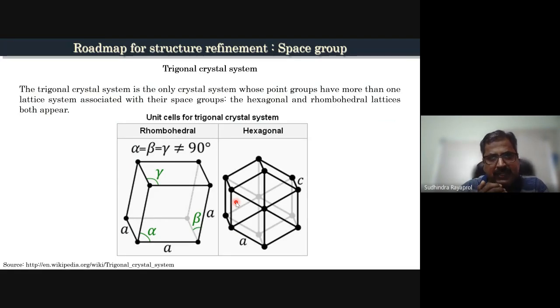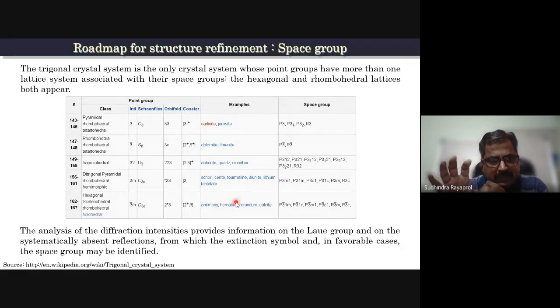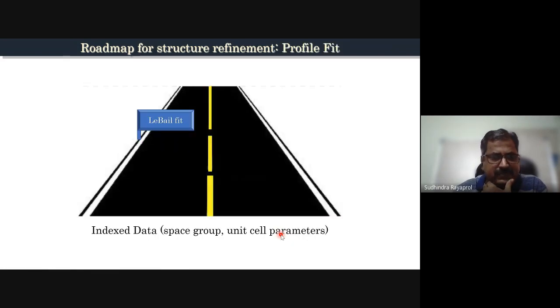Depending on the cell parameters which you have, you should identify the systematic absences of that space group which are allowed or which you have observed. So it's a combination of that. It's a trial and error method. You will come to a set of space groups which satisfies those conditions of the HKL and the cell parameters obtained. This is done automatically using the Select program for a single crystal, but for powder diffraction, it is a little bit more involved method. The best way of doing Rietveld refinement is to have a starting model and use that model, that space group and cell parameters, to identify the cell parameters for your sample. So the next step, once you identify the space group, is to carry out the Le Bail fitting.